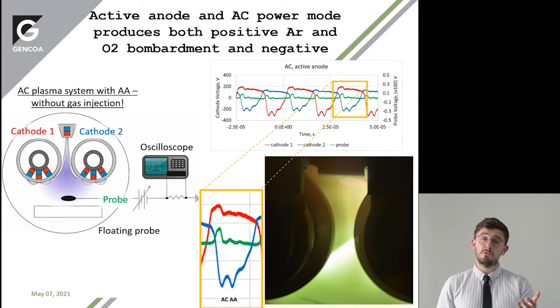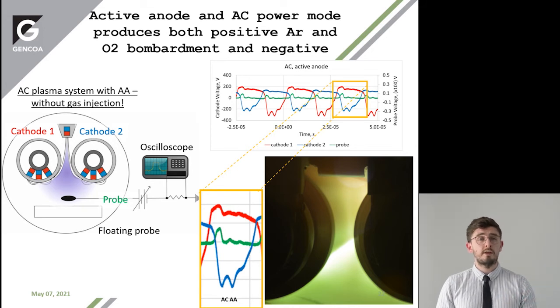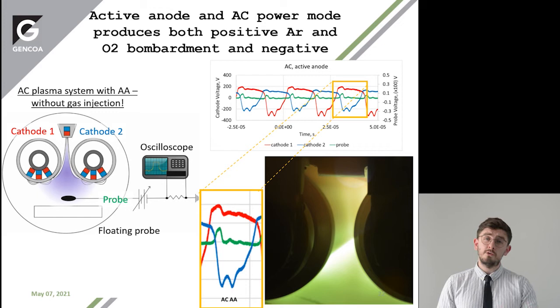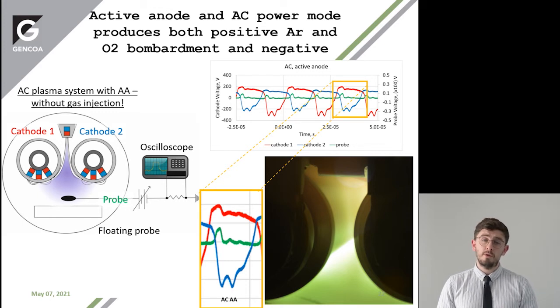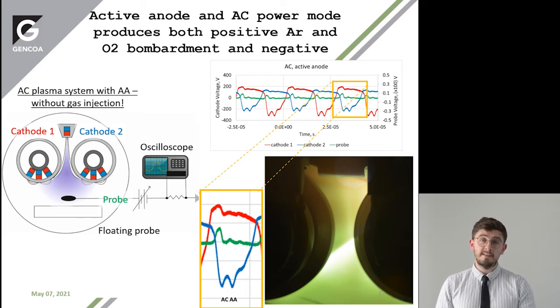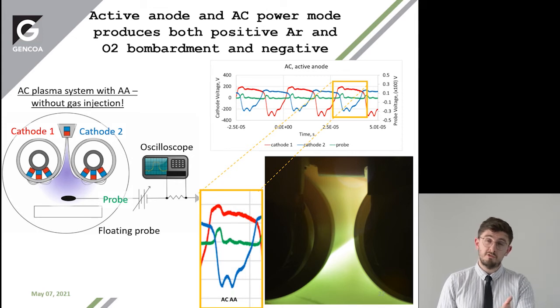These are the voltage waveforms without the gas being injected through the walls. For each cathode, we've taken a voltage waveform, and then using a floating electrostatic probe, we measure the voltage. This is indicative of the current which we would get to a floating substrate such as glass.